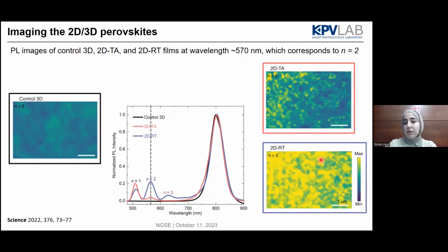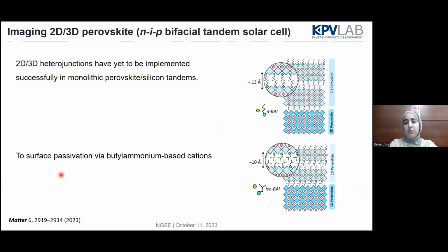On the other hand, here you have really strong excitonic emissions. In this case, we don't care about this really uniform formation because this wasn't the PIN structure, so we don't care about the exciton binding energy. But in my case, for these N-butylammonium and isobutylammonium, the formation of these was important.